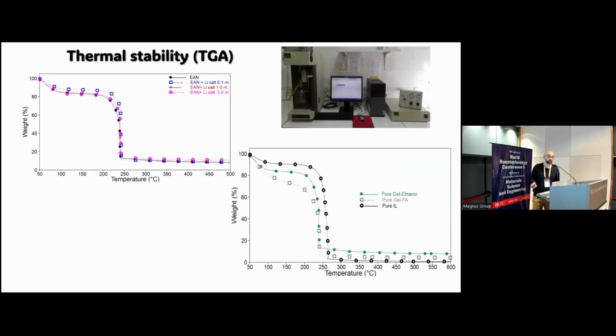We have also determined the thermal stability of our pure compound with lithium salt. You can see that there is practically no difference between the pure ionic liquid or when we add the lithium salt. And even the same with the gelation. There is practically the same thermal stability. You can see here a small decay on the curves. That is probably due to a small amount of water or the residual of formic acid or ethanol from the synthetic route.